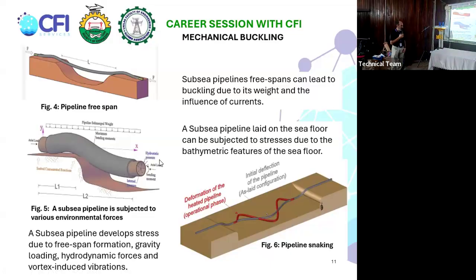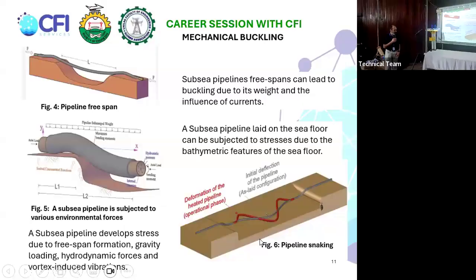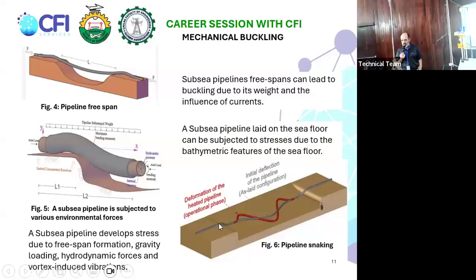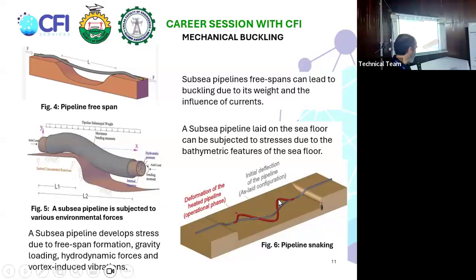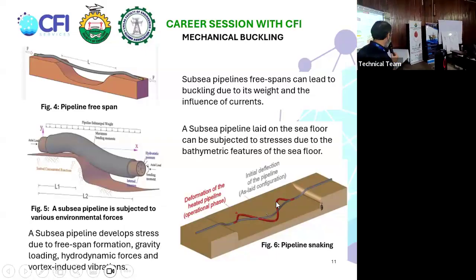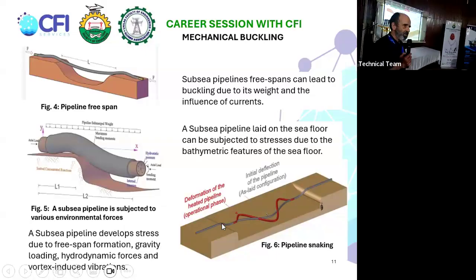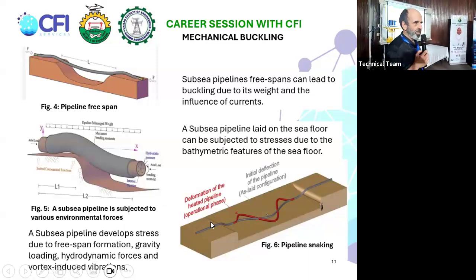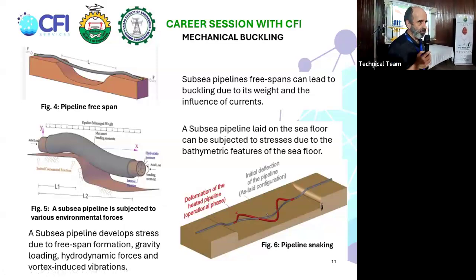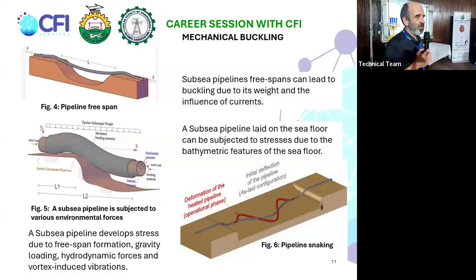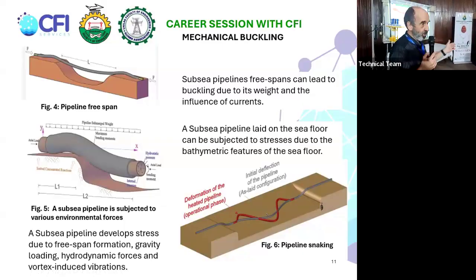Another one that you see on the right on figure 6 is the snaking, which could be caused by currents also. If you have a long stretch of pipeline and it's on an area of mud where there is not much friction, the currents might start moving the pipeline around and it forms this S shape. And so either by fatigue or by the shape of that curvature it could lead to buckling as well in that case. So you never want to install a pipeline without studying on-bottom stability.